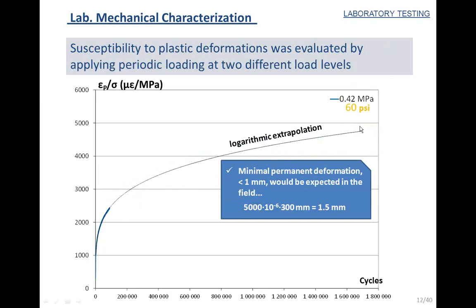Besides, we made a logarithmic extrapolation. Here you have the information concerning the 0.42 megapascal, which could be the level that we have right below the asphalt layer at the top of the cement-stabilized material. There was a very nice fit with a logarithmic model, and here we did a logarithmic extrapolation up to 1.7 million cycles, because this is the maximum number of load cycles that we have been applying in the test track. And even for this maximum number of cycles, the plastic strain is below 5,000 microstrain. So yes, this is a very rough number.